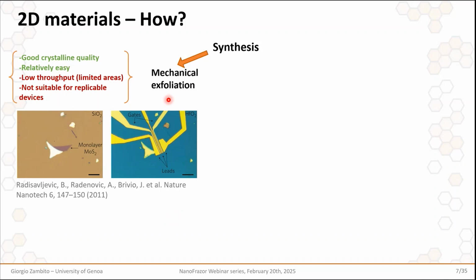So the first one is mechanical exfoliation, which is, we may say, the most known way to obtain layered materials. And this kind of approach, which is the same that was exploited for first graphene isolation in 2004, is kind of easy to perform, and it gives you very good crystalline quality material, but you are kind of limited in terms of areas, generally at the microscale. And as a consequence, it is not really suitable for creating replicable devices, replicable geometries in an on-demand fashion.